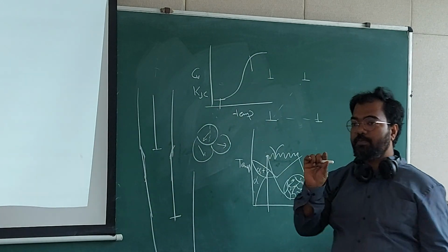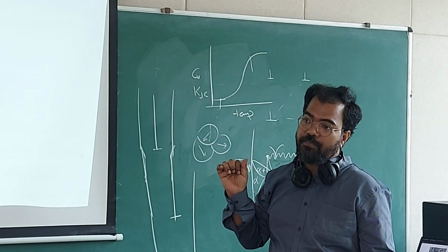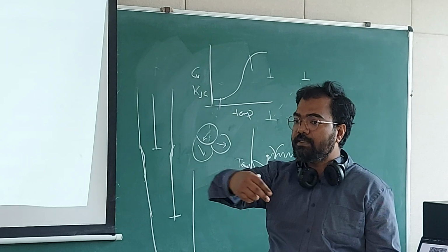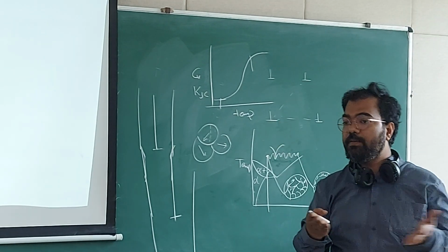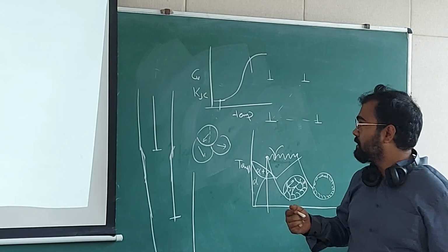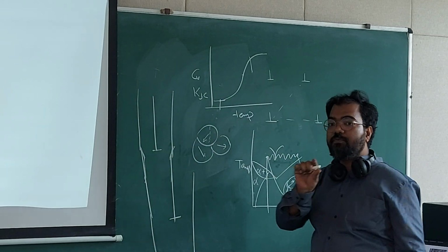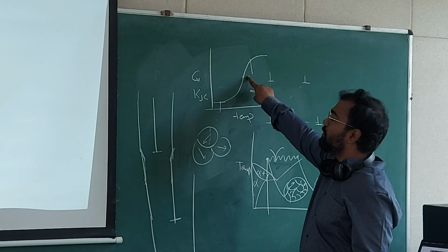What happens first? There is a little bit of plastic deformation happening on the lower part, and then depending upon how many carbides are there at the crack front, that decides the probability of fracture, and it breaks, it fails. Okay, this happens. Then you go above, and you will have more plasticity happening. So the amount of plasticity is increasing as you increase the temperature.